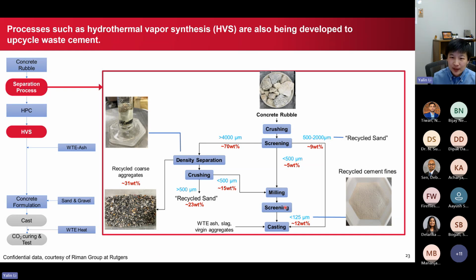For example, here I'm showing the schemes of another process which starts with a similar process of crushing the concrete rubble, but here they involve a wet separation using density to separate the fine aggregates from the cement. These are essentially the recycled coarse aggregates, and then the cement fines they recycle from this process. And there's also the hydrothermal vapor synthesis, which is another process they use to reactivate the recycled waste cement materials.